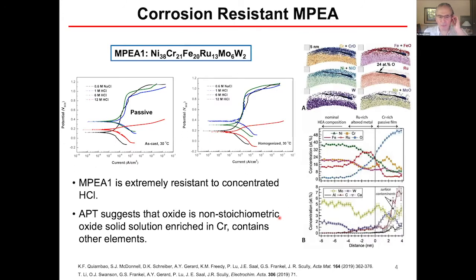Okay, so just as a matter of introduction, we started with this alloy. We're calling it MPEA1. Okay, and John Scully already introduced you to it a little bit and showed you what great properties, what great passivity it had, and he showed some of the atom probe tomography results. Didn't really dwell on them, but talking about the oxide, which is a non-stoichiometric solid solution oxide enriched in chromium, but containing all kinds of other elements shown in here. What I am showing you on these polarization curves are for both the as-cast material and homogenized.